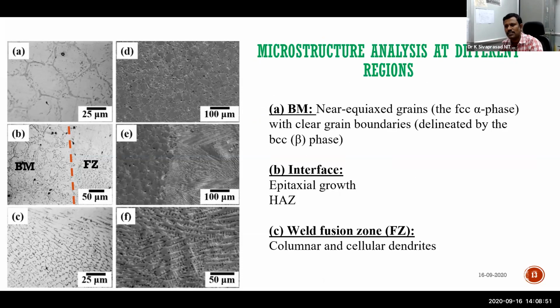So in the microstructure analysis at different regions of the welded joint, we have seen a similar kind of variation. Normally from TIG welding to electron beam welding, a good amount of deviation should be there. But here we got almost similar structure, only relative fineness we have observed. Microstructural features are almost the same, but relatively finer. That's what we have observed.